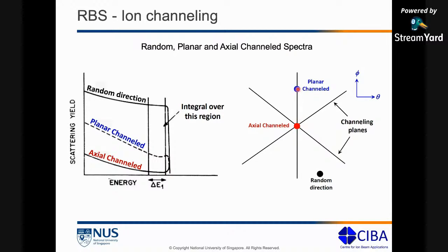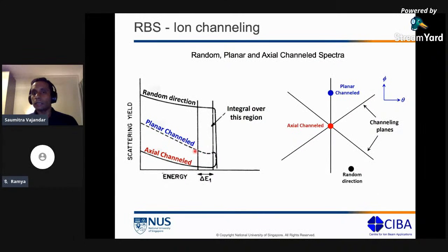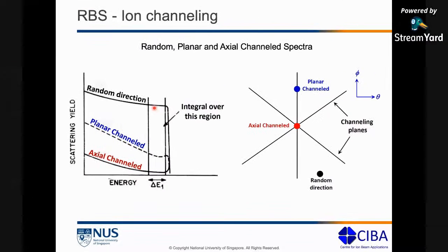If you're on the plane somewhere here, what you're going to get is a planar channel spectrum, and in this case, your backscattered yield will be slightly higher, not as good as the axial channel spectrum. You will still have a surface peak, but your backscattered yield will be slightly higher. And of course, if you go off these two points somewhere here, which is the random direction, your backscattered yield is going to be fairly huge. Okay, so for the sake of materials analysis, what we are usually concerned with is the random direction and the axial channel spectrum. We want to find out the difference between this and this. We are not really concerned about planar channeling.